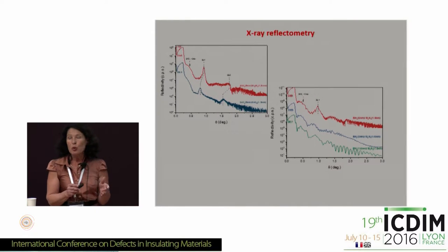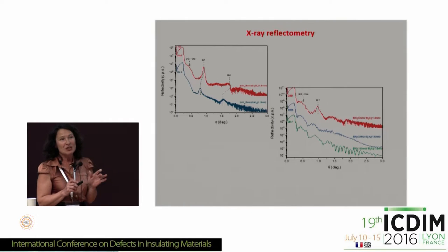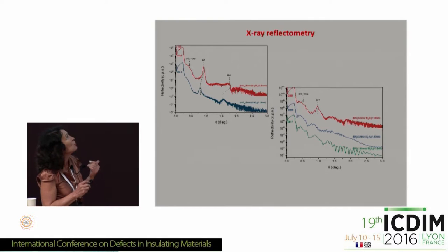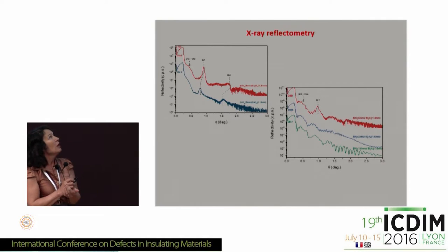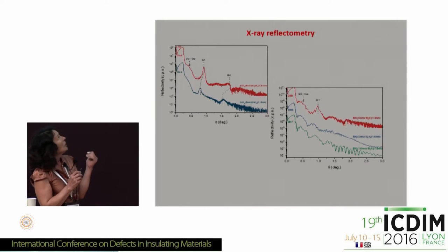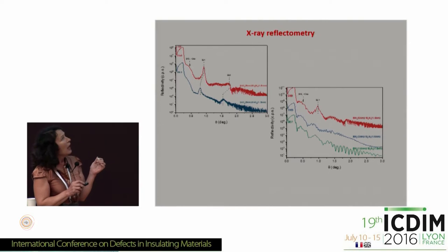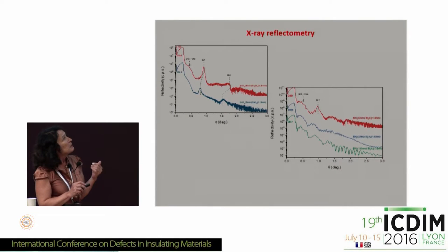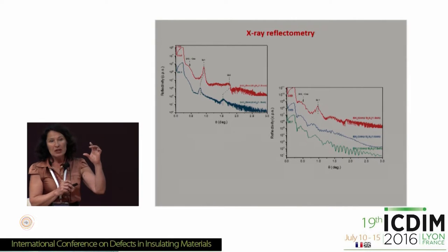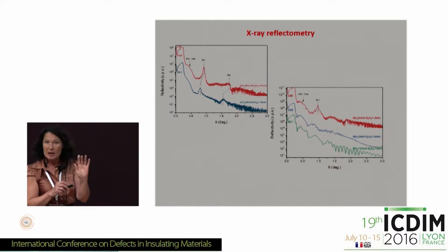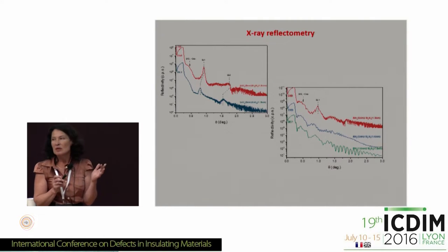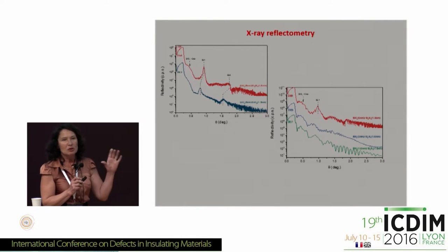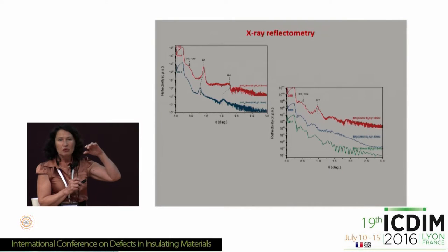I want to report quite new results, which were not properly analyzed yet, but they are quite fresh. We used X-ray reflectometry to check the layer structure of our samples. The figures show three types of oscillation frequencies: one corresponds to the whole thickness of the total number of layers, another to the pairs of layers. Even after annealing, some layer structure is preserved in some of the samples. We had an additional peak indicating structures of 10 nanometer size, which appeared to be a capping of the samples.